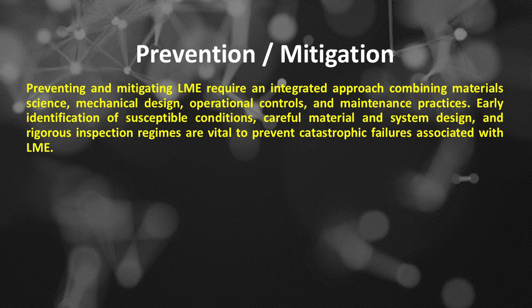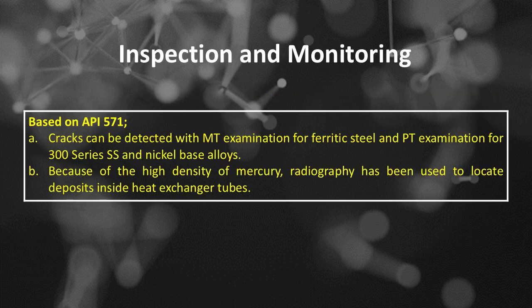Liquid metal embrittlement or LME damage inspection and monitoring based on API 571. Number A, cracks can be detected with MT examination for ferritic steel and PT examination for 300 series SS and nickel base alloys. Number B, because of the high density of mercury, radiography has been used to locate deposits inside heat exchanger tubes.